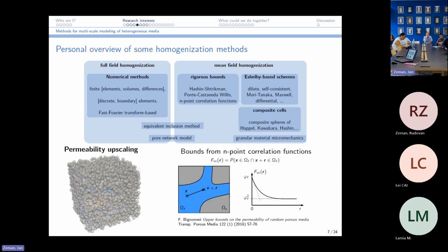Then for the part about the rigorous bounds, instead of solving this whole problem using extensive numerical means, I've tried to estimate the permeability by using reduced microstructural information. So not the whole RVE, but just some information. One primary piece of information is the porosity, and we could add higher order information, such as n-point correlation functions, which are spatial correlation functions that give you statistical information. For example, the 2-point correlation function of the fluid domain could be the probability of finding 2 points x and x plus r both in the pore phase, given that they are separated by r, which is fixed, but x is moving everywhere in the microstructure.